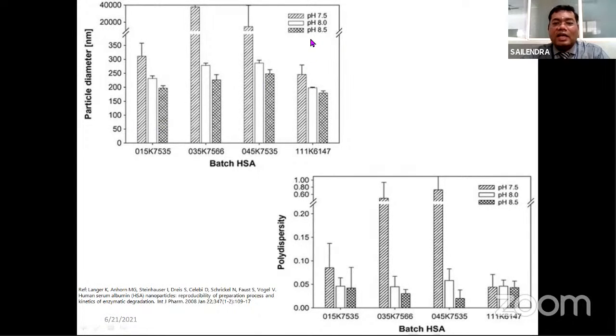Whenever you are having a highly alkaline pH, somewhere around 8.5, you see the particle diameter keeps around 150 to 200 nanometers. Now, if you are having a pH of 7.5, you are having a high particle size, and at pH 7.5 you are always seeing particles above 300 nanometers or above 250 nanometers. So alkalinity of the medium is also one of the important parameters while you are preparing the particles.